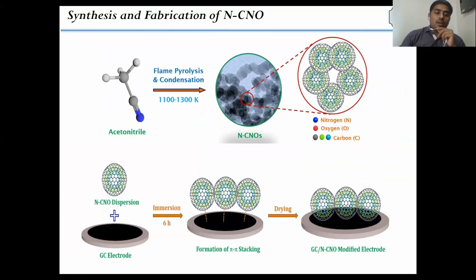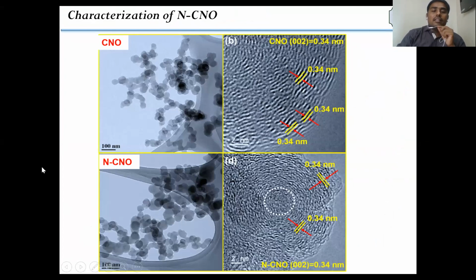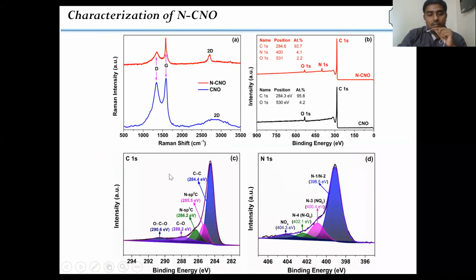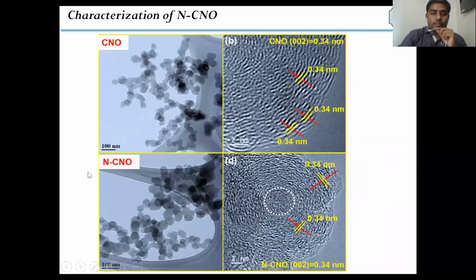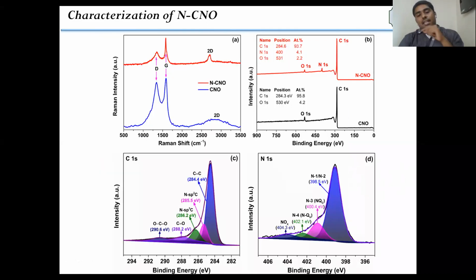The carbon nano-onions were fabricated on the substrate, and the fringes from the HRTEM image exhibited the formation of carbon nano-onions. See the layers of onion-like structure, carbon nano-onions and nitrogen doped carbon nano-onions from the TEM images. And from the XPS analysis, we confirm there is a nitrogen doping.